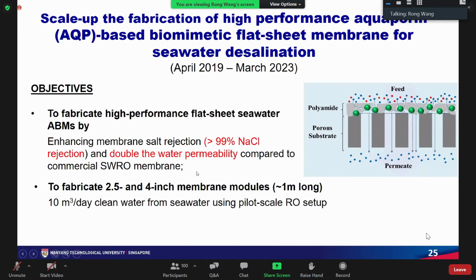The objective is to fabricate high-performance flat-sheet seawater aquaporin-based membranes by enhancing the salt rejection to over 99% for sodium chloride and doubling the water permeability compared to the commonly used SWRO membranes in the market. In the second phase, we will scale up the membrane fabrication to make 2.5-inch and 4-inch membrane modules. And we will build a pilot with capacity of 10 cubic meter per day clean water from seawater using our biomimetic membranes. That's a very challenging task.